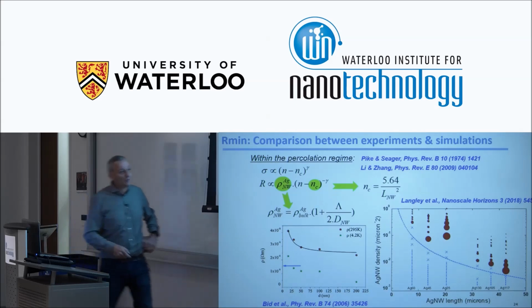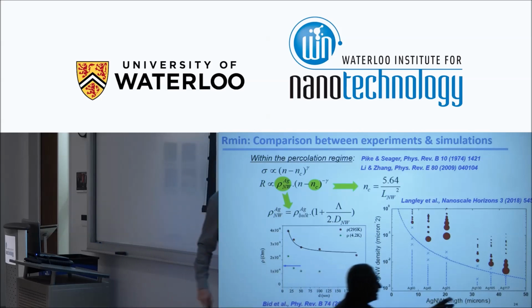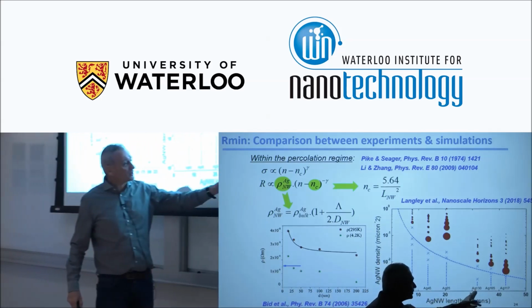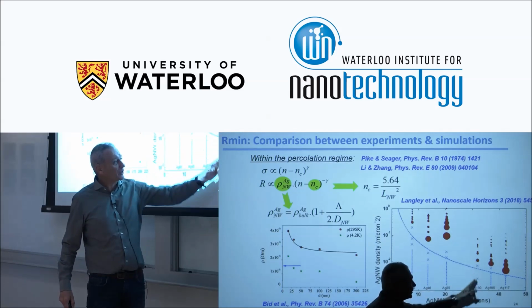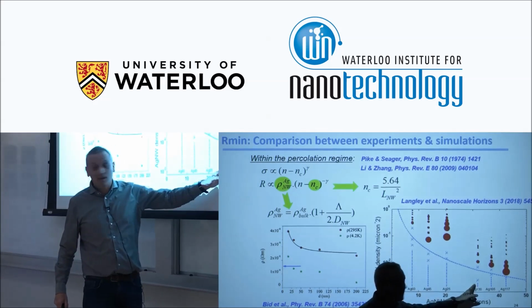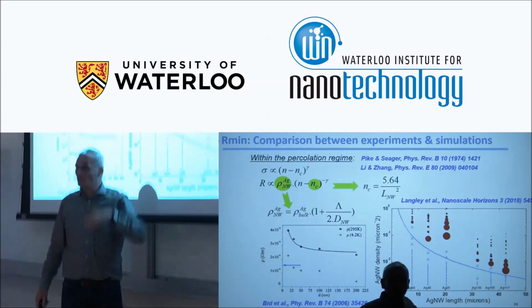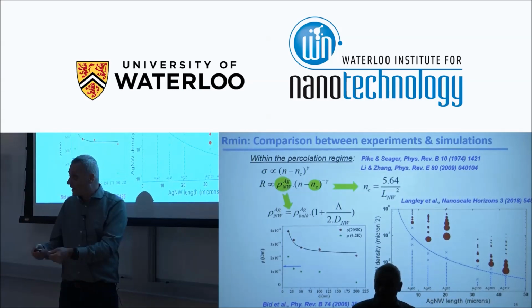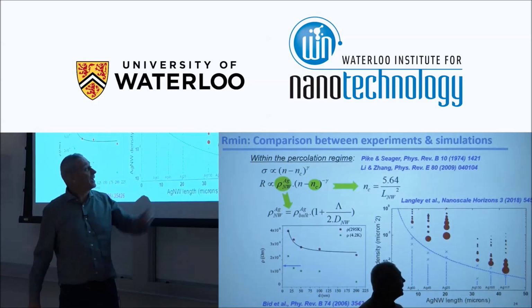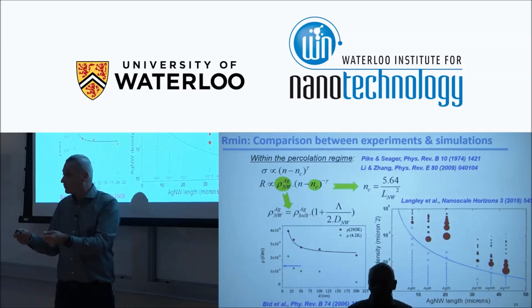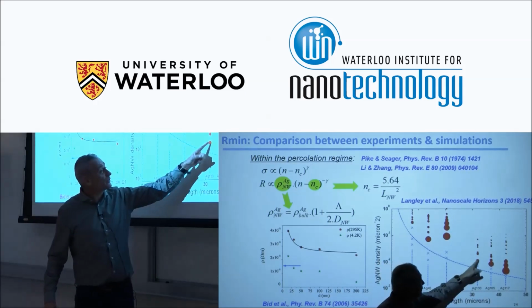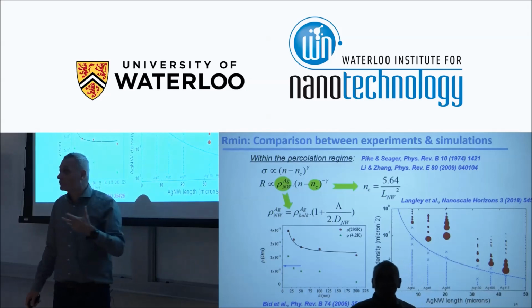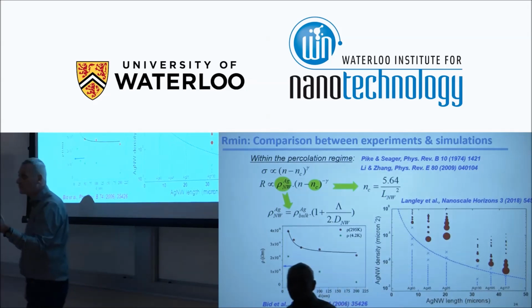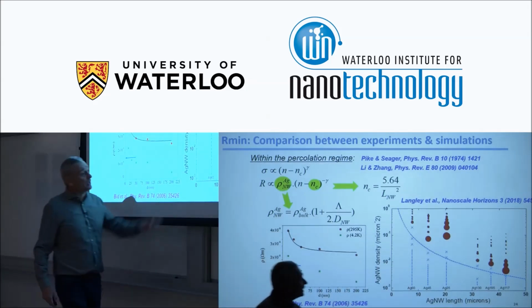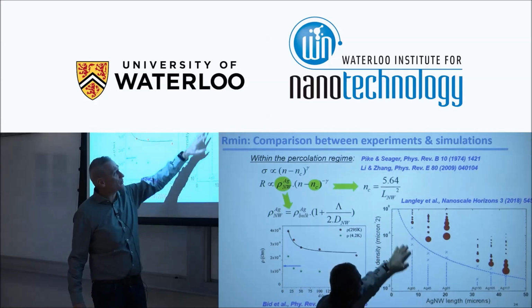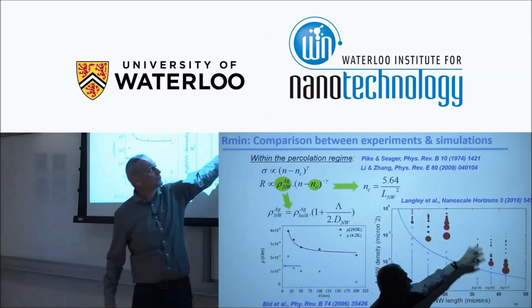Okay? And for example, for one given length of nanowires, we fabricated different networks with different density. When it's a cross here, that means the network was not percolating. We were not able to measure any finite electrical resistance. And in red, we were able to measure some resistance. And the diameter of this disk is directly proportional to the log of the resistance of the network we measured. Okay? So it's a kind of phase diagram. Here we are supposed to have no percolation, and here we are supposed to have percolation.